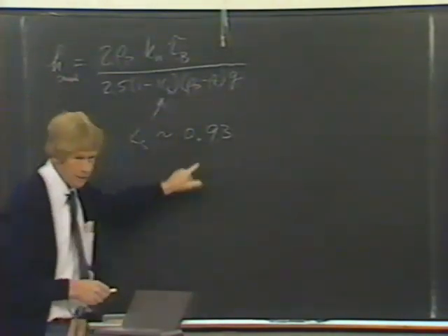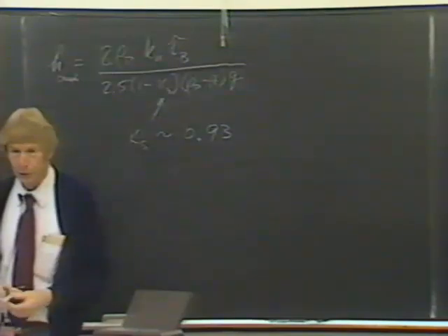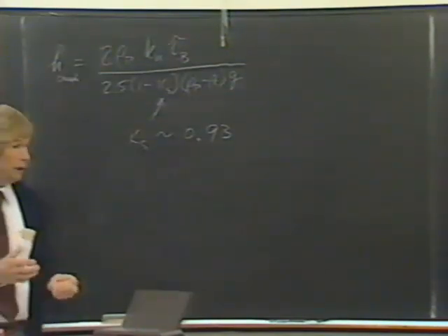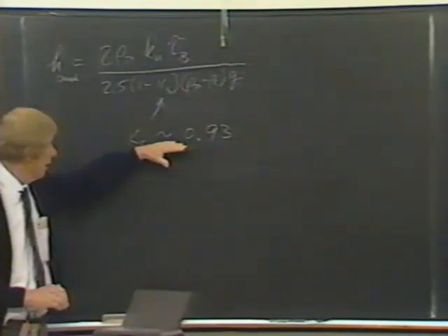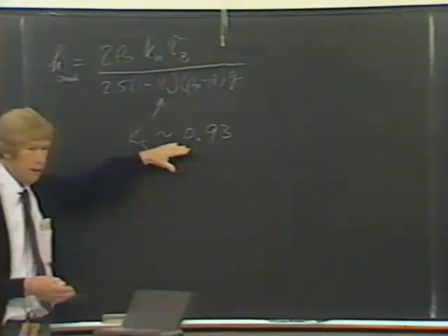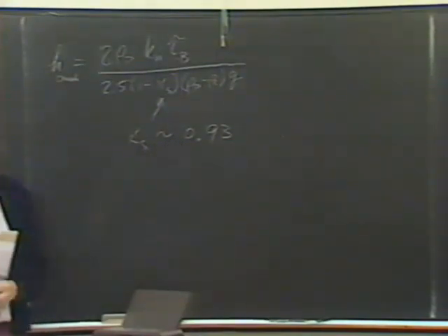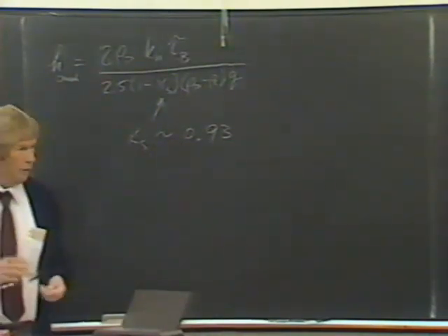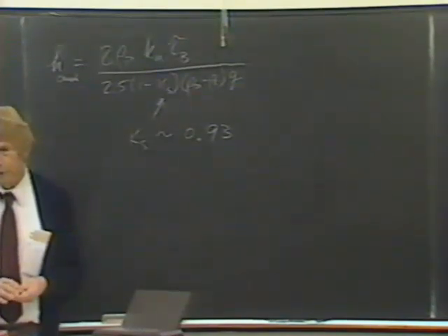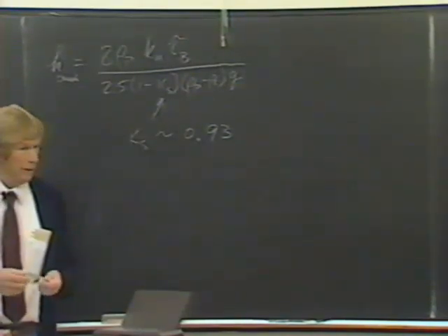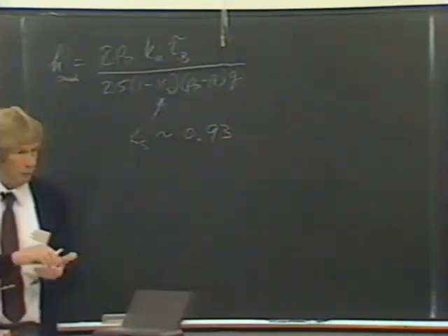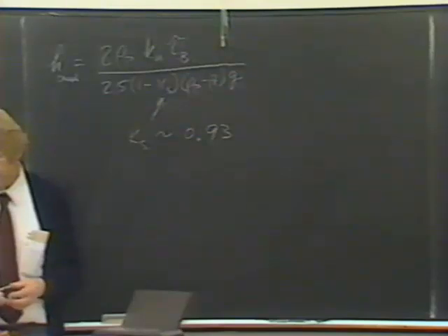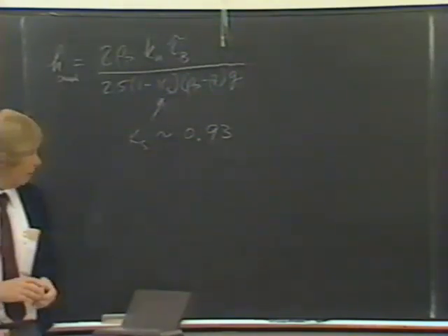Now this data supports the description of structures as being aggregates of aggregates, because the larger pores would crush first, and the smaller ones would crush later. So it looks like this bed, at least when it first deposits, is a collection of aggregates, as we discussed earlier. Now what about the gelling? I'm going to digress quite a bit and talk about gelling because that is important.